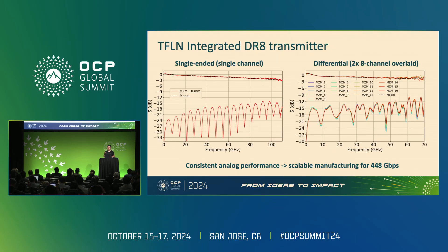We made two types of modulators. The first is a single-ended electro-optic modulator with a measured EO roll-off up to 110 GHz, very close to theoretical expectation — giving us a good understanding of the analog behavior. The differential response measured across two chips (16 channels total) shows that electro-optic responses lay exactly on top of each other, with differences only within measurement noise. This means extraordinary analog performance is achievable in a very scalable manufacturing way — you may not even need to individually test every channel at these extraordinary frequencies, which has been a major roadblock for high-speed analog components.